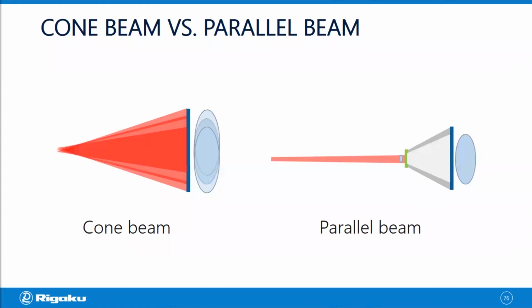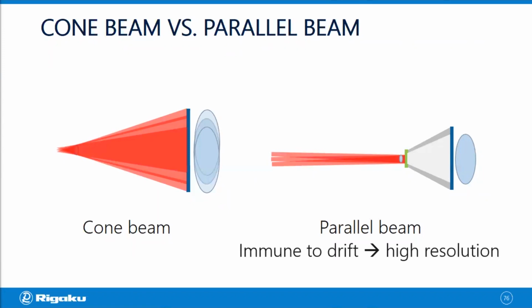microns. If you use a parallel beam geometry, even if the source drifts a little bit, because you're not using X-ray divergence for magnification, your image doesn't get blurred. So you can say the parallel beam geometry is immune to drift. And that's why this geometry works better for high resolution. And with the parallel beam geometry, you can probably achieve about 1 micron and sometimes even a couple hundred nanometers resolution.